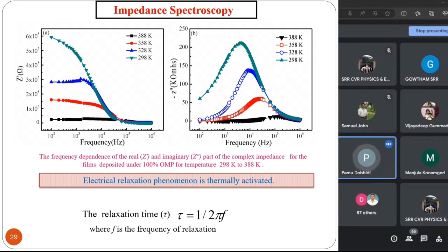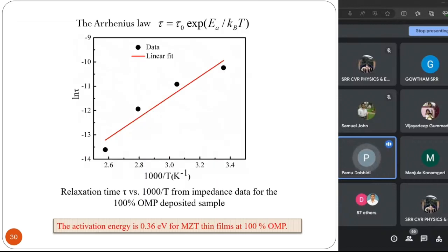Yeah, next slide, please. Yeah, so here also you see that the relaxation time is there, and from this also we see that in this case the activation energy is less, because these are thin films which are only about 200 nanometers. That's where the activation energy in this case is smaller, but in the previous case the activation energy is much higher. Why? Because you are having a bulk material there.